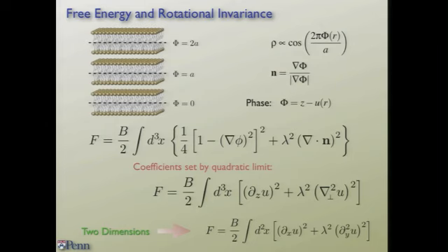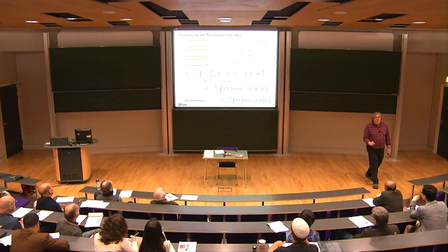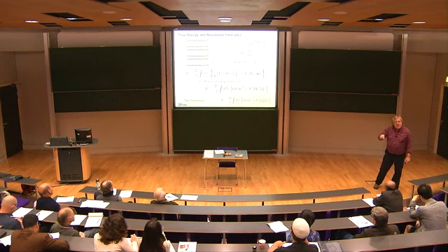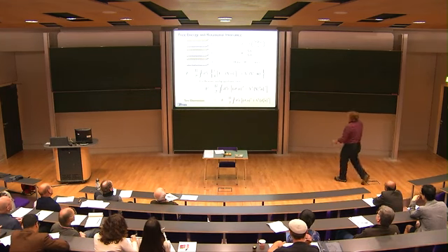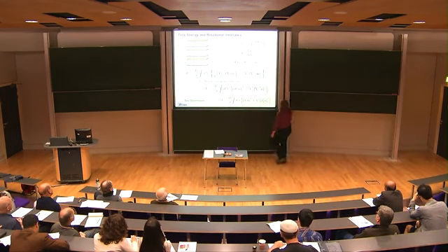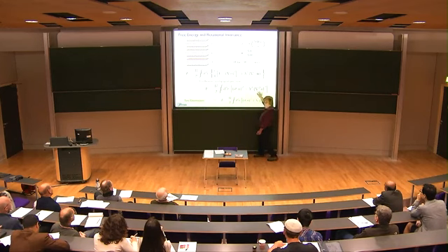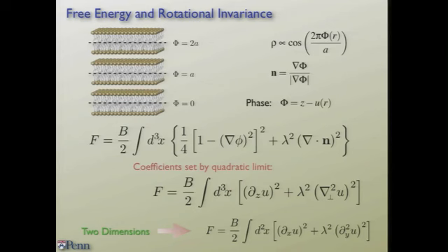And so what can we all agree upon? We can all agree upon the quadratic theory. We can all agree upon what Goldstone's theorem forces us to agree upon, that there has to be some low energy modes, there's some quadratic expansion in some kind of phonon field, which represents a spatially varying version of the global translational symmetry, and we can all agree that this is the theory of smectics for small displacements.